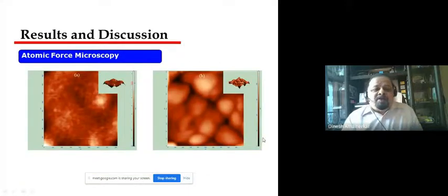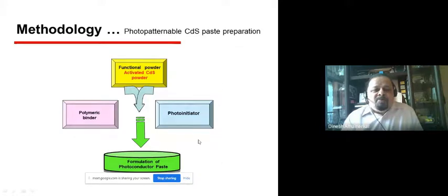And this is the atomic force microscopy, because I just said that you need to get a 30 micron line, or maybe a 100 micron line in this case, we cannot have micron scale activated photoconducting material, that is cadmium sulfide. And this AFM confirms to some extent that we are getting, if not nano, at least a submicron size of nanoscale cadmium sulfide doped with chlorine compensated copper. Now, we have got a functional powder, like activated cadmium sulfide that is doped with copper and chlorine. Then we mix it with binder and photo initiator and formulate a paste.